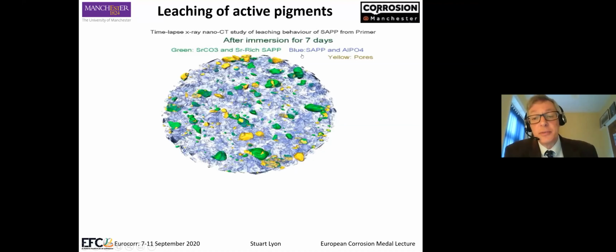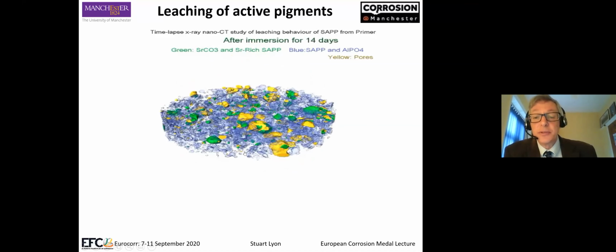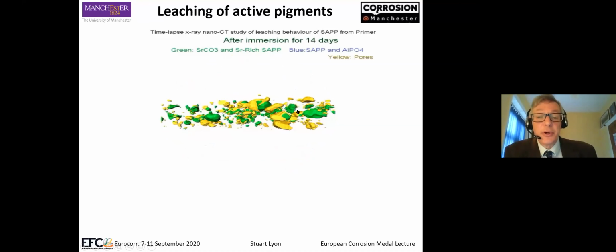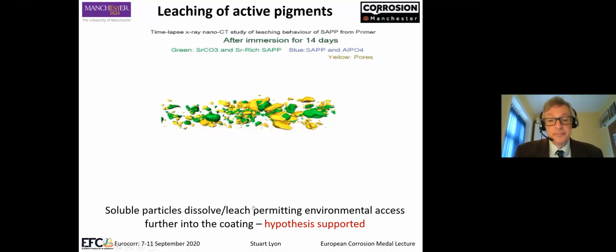Some of this functional material is not leaching, or not leaching within the resolution of the instrument, but some is. And clearly this is part of the mechanism. So soluble particles dissolve and leach, permitting environmental access further into the coating. And so we think that hypothesis is indeed supported in this particular case.